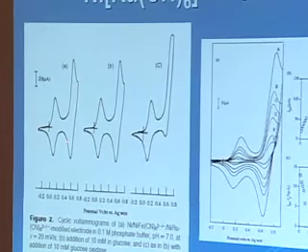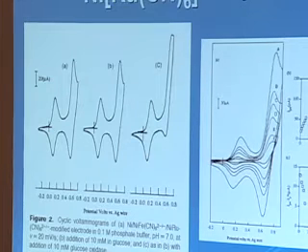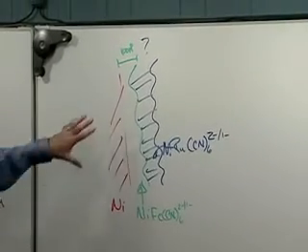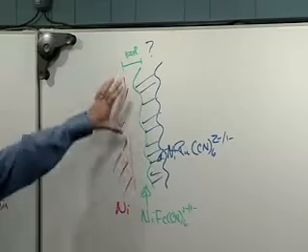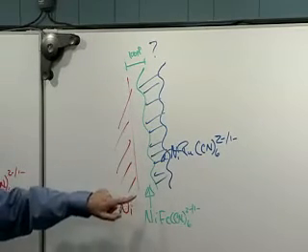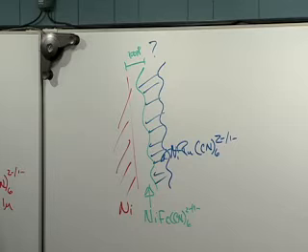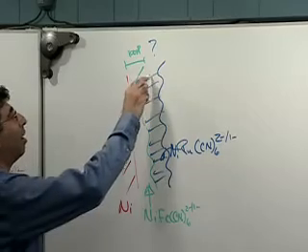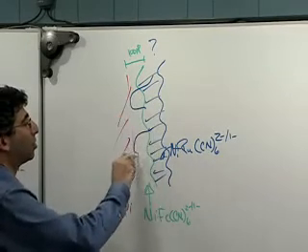So the irons are not strong enough oxidizing agents, based on the cyclic voltammogram, to do this. Even though we laid this layer down sequentially, this can't be the right picture. We could never get that cyclic voltammogram from this picture. We should have just seen the nickel ferricyanide and not the ruthenium. So probably what happens is that when the ruthenium goes in, it steals nickel ions out of this ferricyanide lattice. In doing that, the ferricyanide to some extent falls apart, and so we have regions where the ruthenium gets down to the surface.